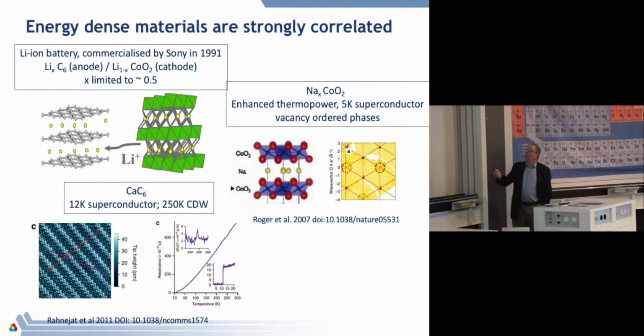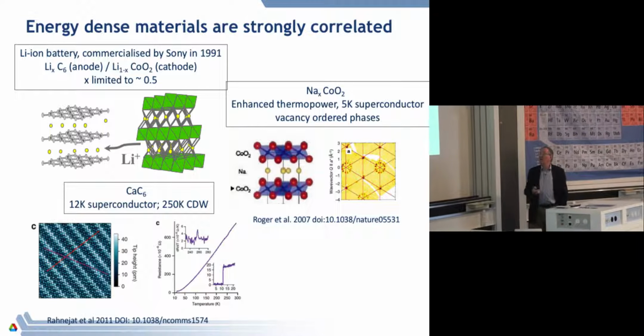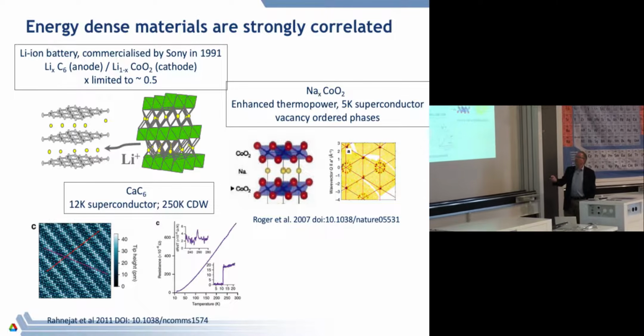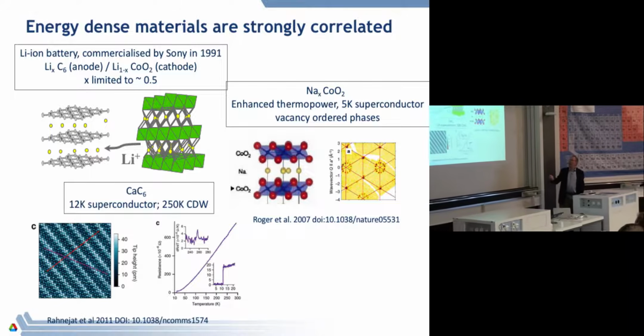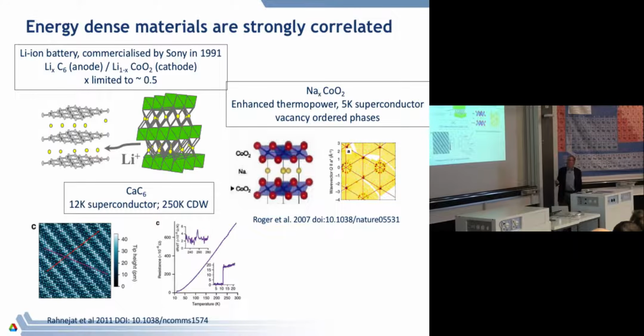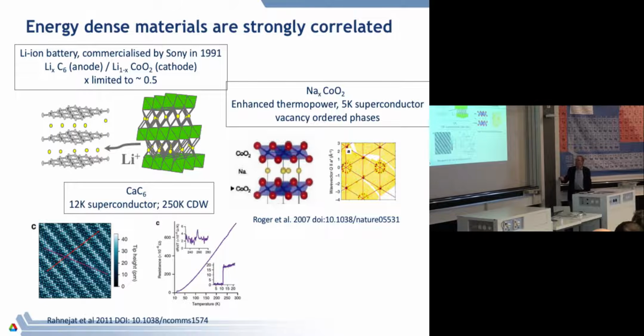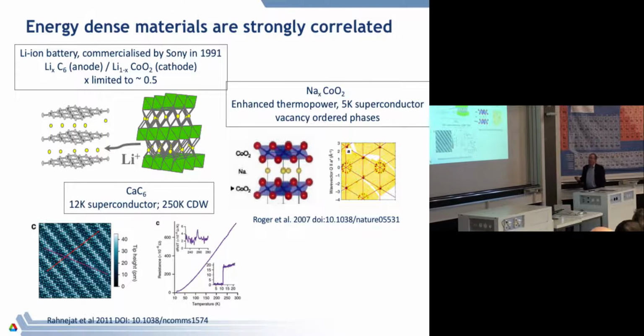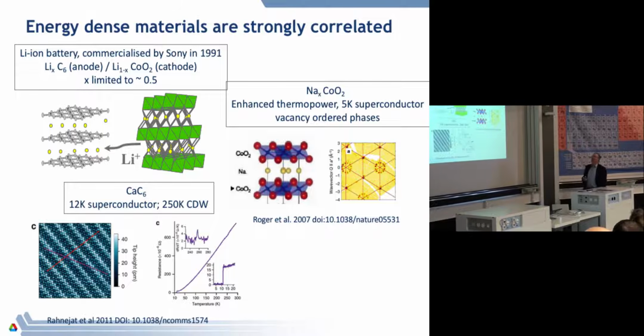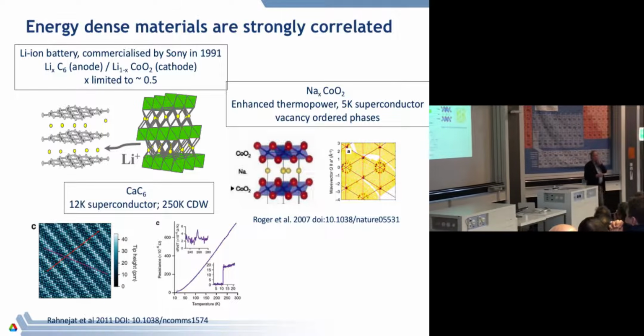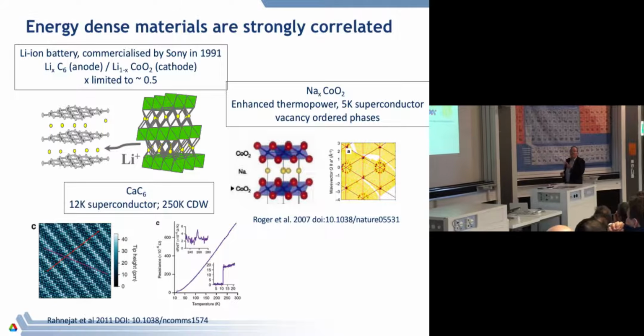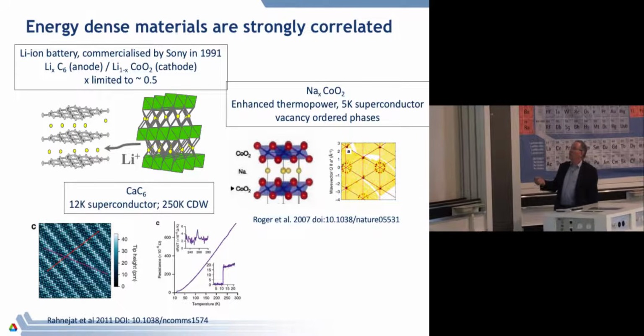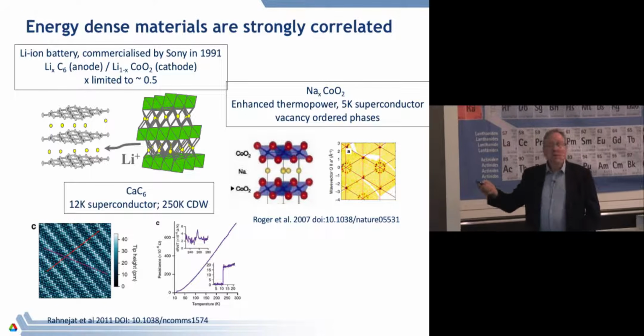And if I go from lithium to calcium, calcium is charged 2, so I'd like to be working with an ion like calcium rather than an ion like lithium in a battery. But this material actually produces an ordered density wave state at about room temperature, and also is an enormously high temperature superconductor, around 12 Kelvin. Okay. So there's an interplay between the materials that we want to use for one class of technologies and the problems that come across for the other.